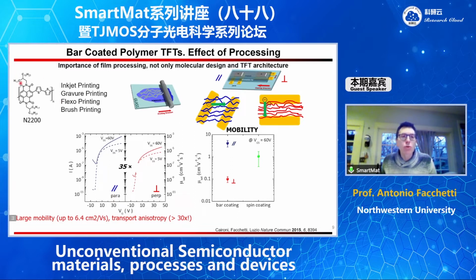The polymer has been, as I told you, processed using many methodologies, going from inkjet printing, gravure printing, flexo printing, brush printing, and another technique we have used is bar coating, where the technique can align the polymer chain in the direction of charge transport or perpendicular to the charge transport. And here is the field effect mobility. When you process perpendicular and parallel to the charge transport, you see a large variation in mobility. This is called charge transport anisotropy, and also very large mobility can be achieved.